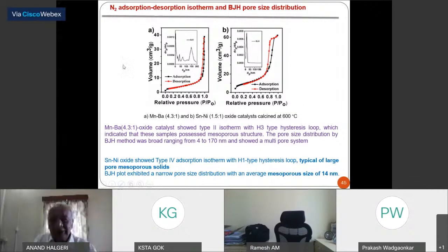To understand the pore size distribution, the measurements, these are the surface area and pore size distribution of the material. Nickel tin oxide shows type 4 adsorption isotherms and average mesoporous material of 14 nanometers. So these are the important class of materials used for carbonate synthesis.